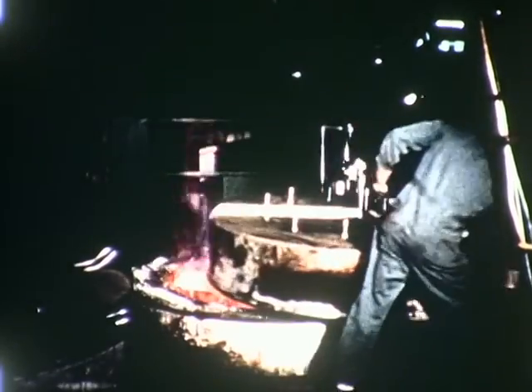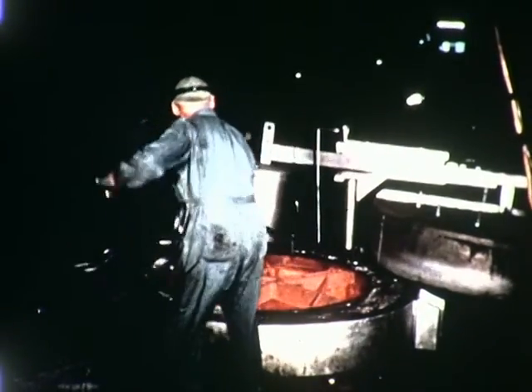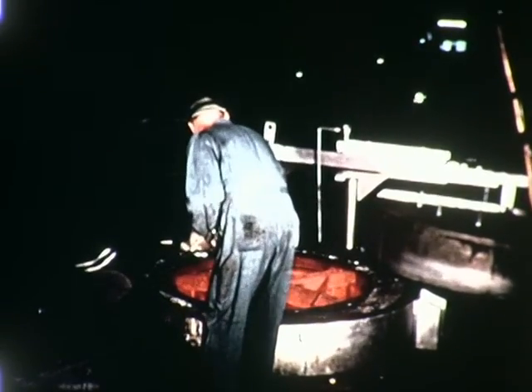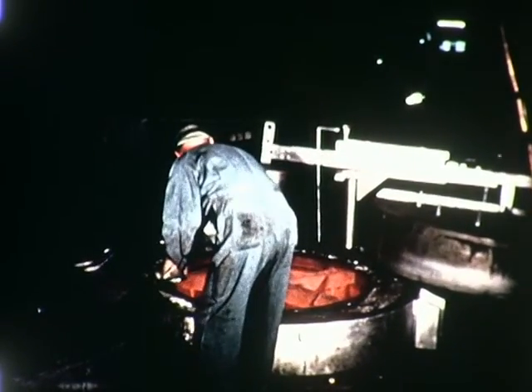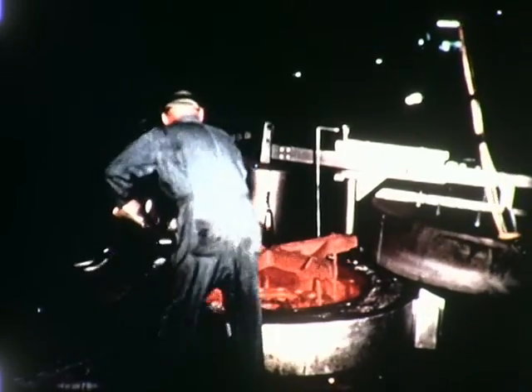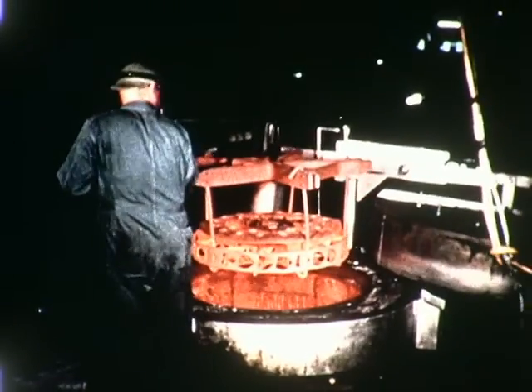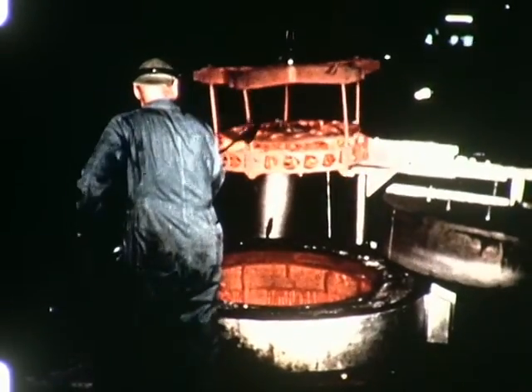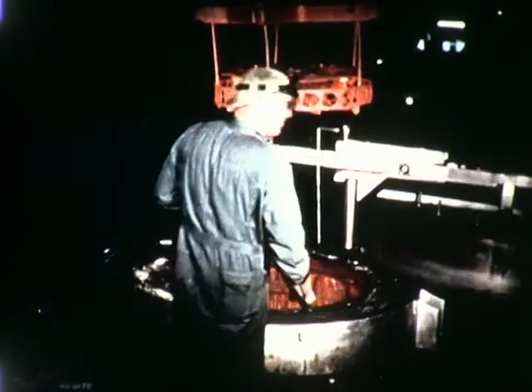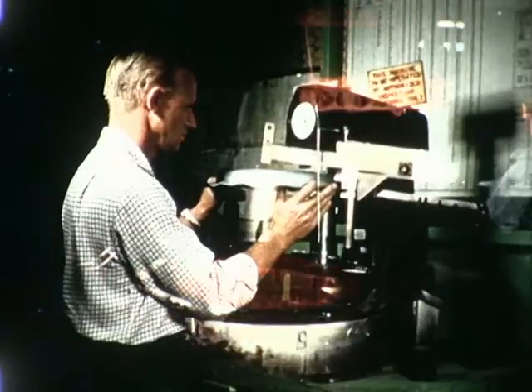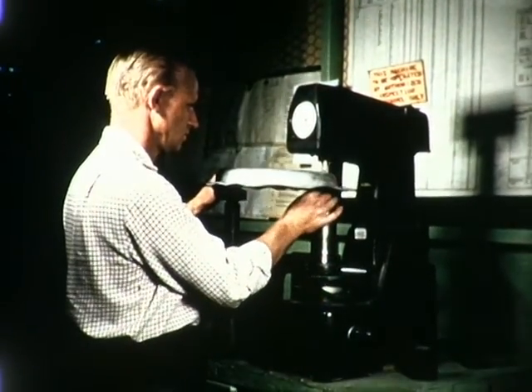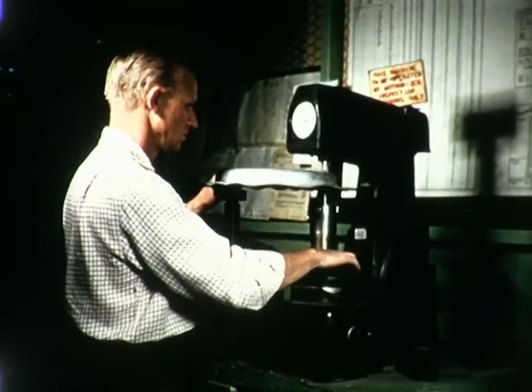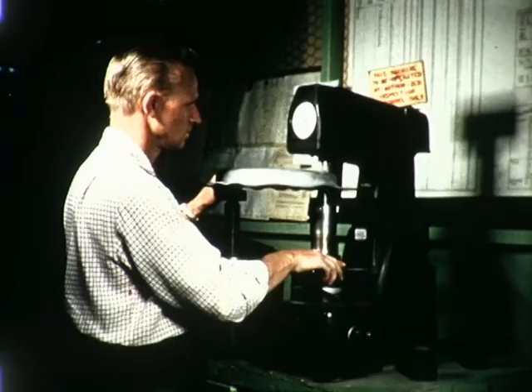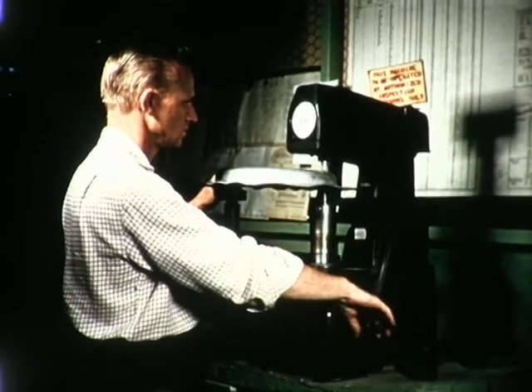The aging of Rene 41 is obtained by heating the material to 1975 degrees Fahrenheit for 60 minutes, followed by an air cool, and then reheating to 1650 degrees Fahrenheit for 4 hours. The aging process gives the material a room temperature strength of 155,000 pounds per square inch. Satisfactory descaling methods have been achieved using standard facilities. All material should be hardness tested after annealing. If a Rockwell reading of C28 is obtained, the material should be re-annealed.